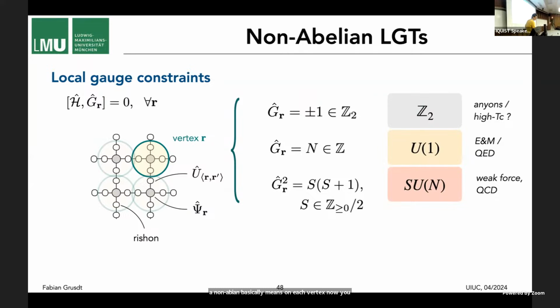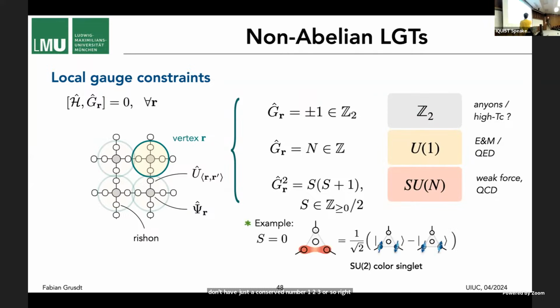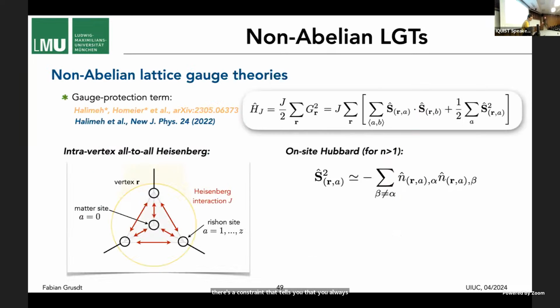So it could be that there's a constraint that tells you that you always have to have a spin singlet within each of these little bubbles. And it turns out in this particular case, again, these Hubbard models come in handy, because if you write down the energy penalty for having a local spin singlet, you can break this up into a spin S.S part and a local spin part.